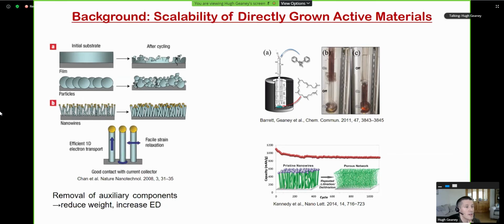Silicon is a very high capacity anode material because it can essentially take on a lot of lithium per unit of silicon. But what happens as a result of that is we get a large amount of volumetric expansion. If we use planar silicon, it will expand and contract and essentially pulverize. The same for films, you'll have a pulverization and a coarsening of the material.